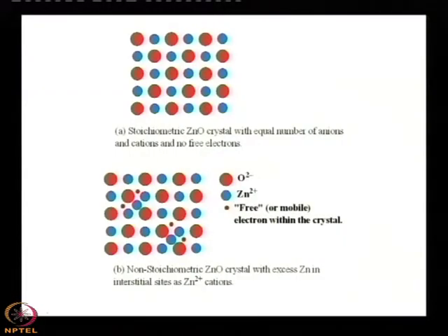Here we have not used any kind of doping or impurity, even then it is n type in nature. Similarly, lead telluride PbTe is p type in nature. It is because of the non stoichiometry, and it is a defect. Obviously, non stoichiometry is a defect, and this has given you the advantage that without doping it is n type in nature.